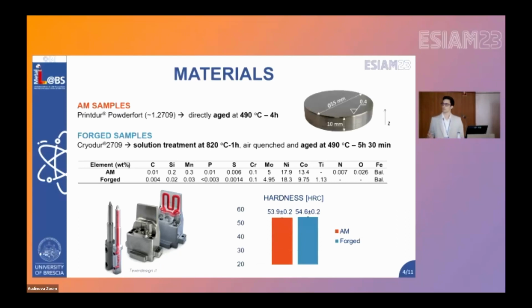Actually, the additive sample needed just an aging treatment, thanks to the supersaturation of alloying elements enabled by the high cooling rate of the laser powder bed fusion process.